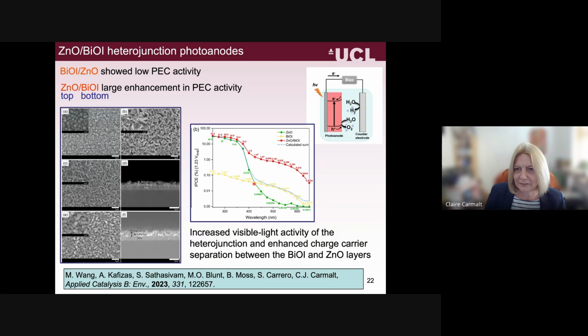We looked at the plain zinc oxide, which is shown in green. We then added those two up to just check it wasn't just giving us the sum of the two. And then this is our heterojunction. And what we see is that it shows significantly enhanced photoelectrochemical efficiency. And what we're seeing is increased visible light activity of the heterojunction. And this is due to, we believe, enhanced charge carrier separation by having the heterojunction present.